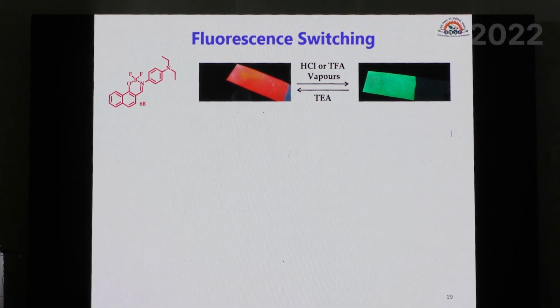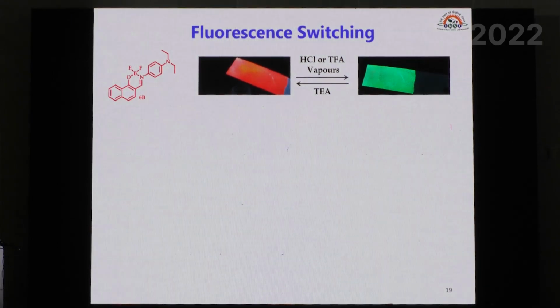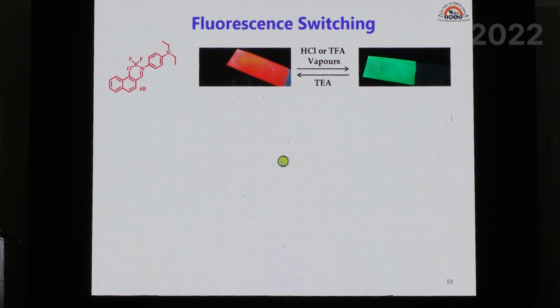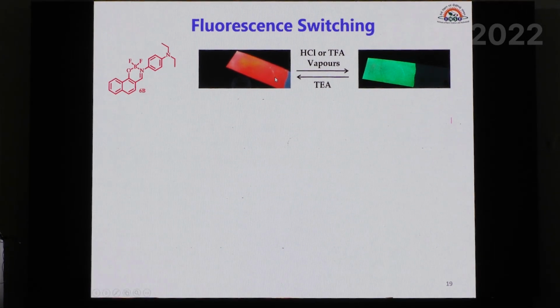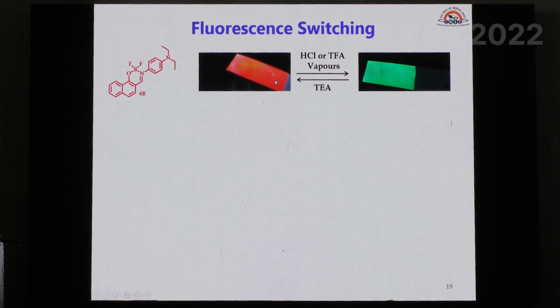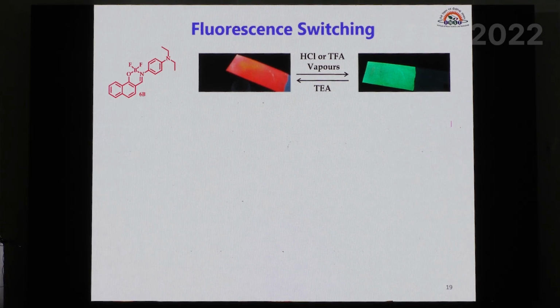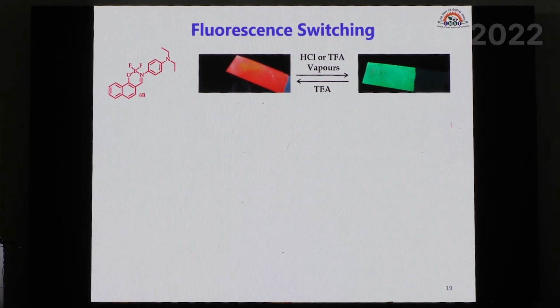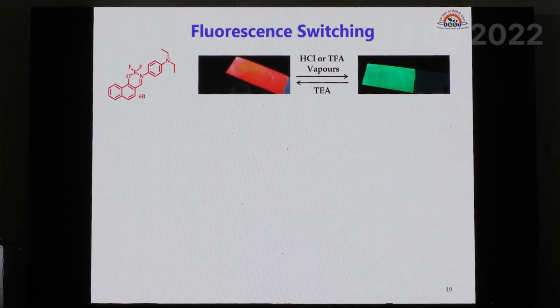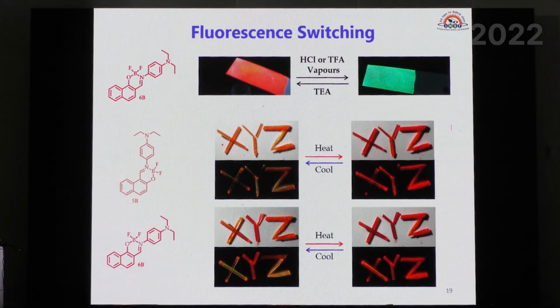Now, this molecule shows a response to acid and to different polarity solvents, so we could develop a test paper strip. This is a simple paper coated with our sample, and if you expose it to acids like HCl or trifluoroacetic acid vapors, it changes color, and you can clearly see that with our visual eyes. And if you expose it to a base like triethylamine, it goes back to the original state. And the crystals also do something similar.